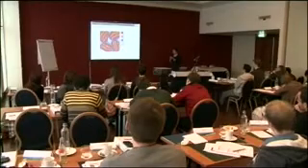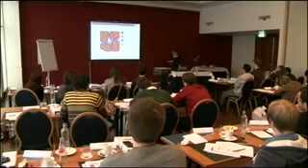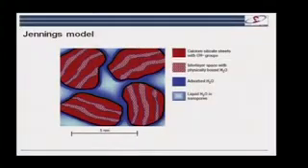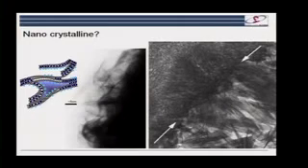And when we come to be concerned with things like transport, this is also why CSH makes life very problematic. So this is the idea of a granular structure with disconnected regions. This is hotly debated because if we look in the transmission electron micrograph, where we have quite a high level of resolution, we're getting down to a nanometer resolution here, we don't see these little grains. And we really would expect to see them now in the transmission electron microscope.